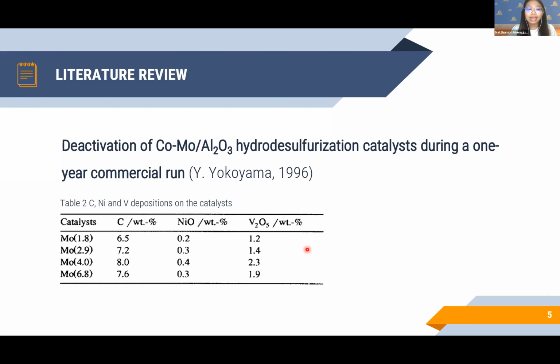The molybdenum disulfide stacks grow in the lateral direction but do not grow in the normal direction to the layer during the HDS run, on the assumption that these clusters are highly active with increased loading. The catalytic activity significantly decreased by aggregation. Table 2 summarizes the amount of carbon, nickel, and vanadium deposition on the used catalyst.